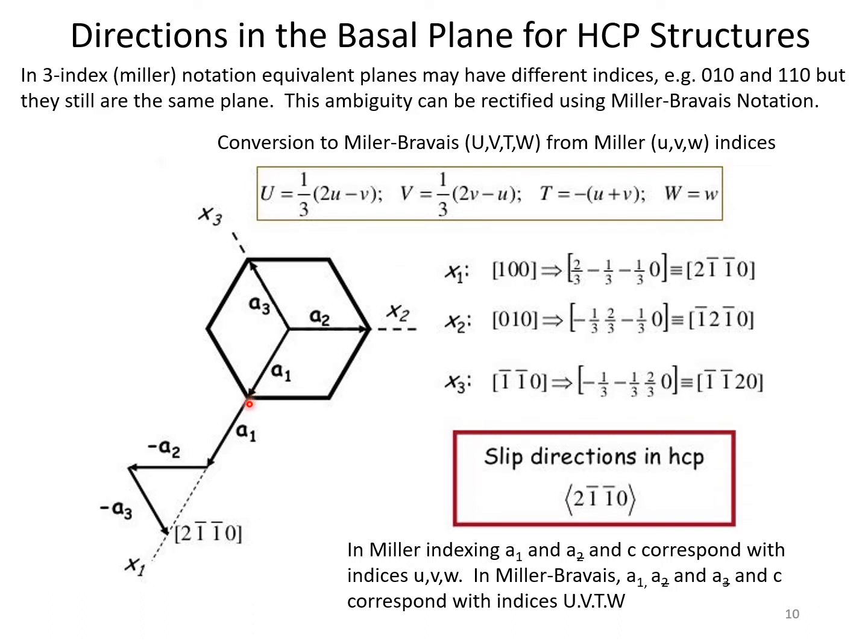we're going from here. We have 2 steps along A1, -1 step along A2, and -1 step along A3 relative to these bases. And that's going from this point as the origin. So that vector going from here to here has a direction 2 bar 1 bar 10. If we're interested in this vector, which would be the distance from an atom here and an atom here, it would be 1/3 of that.